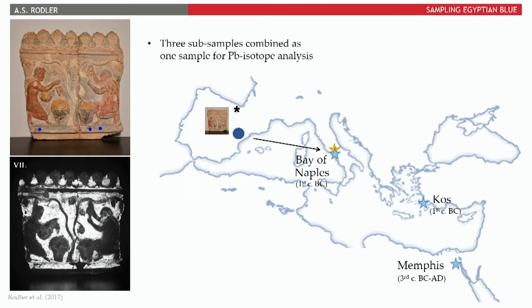Okay, so at first 3 samples were collected and combined for one lead isotope analysis. The 3 samples are here in blue points. So they were pooled together for one analysis, and it gave us a bit of a mixed signal. So what you see here, this potential source area was Iberian copper, all the way to the Bay of Naples, potentially, where the Egyptian blue was then produced and then used for the artifact.